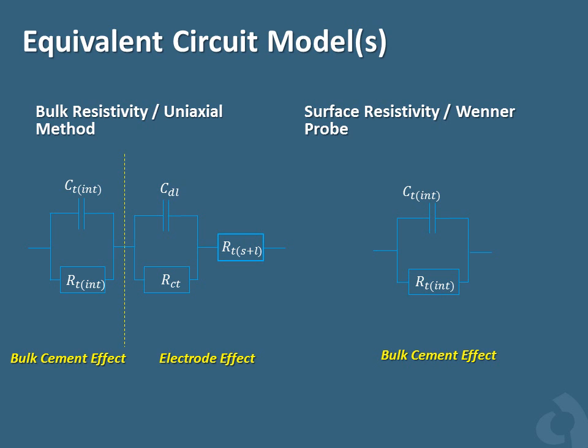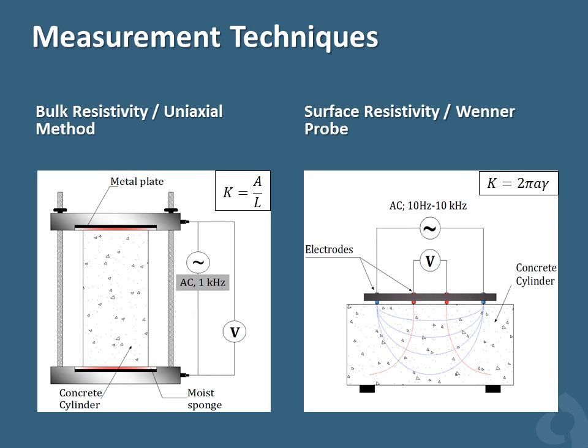In order to find a practical approach to test concrete material, different test procedures have been proposed and put into practice. The electrical response of concrete is normally studied by electrical circuit modeling. This means that concrete acts as an electrical circuit with real resistance and capacitance behavior. The response of such a system is normally determined with the aid of an equivalent circuit model. These models represent the electrical properties of concrete, as well as the electrode-concrete interface. Based on the proposed models, different measurement techniques have been developed, including two-point uniaxial and four-point, also known as the Wenner probe techniques.